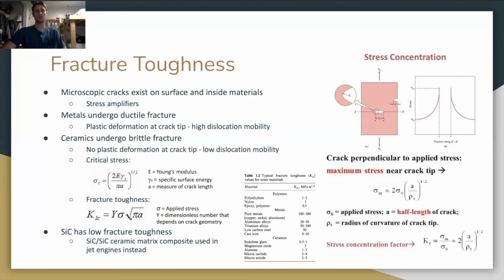It has units of megapascal square root meters, and a lower K1C means that a material will fracture under a lower applied stress. The fracture toughness of silicon carbide is 2 to 4 megapascal square root meters, which is very low. To avoid fracture in jet engine parts, they're instead made from silicon carbide ceramic matrix composites, which I will refer to as SiC CMCs.